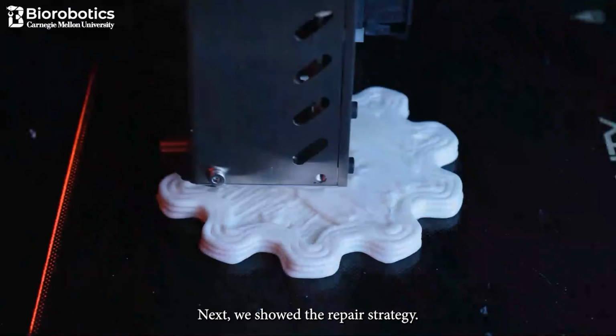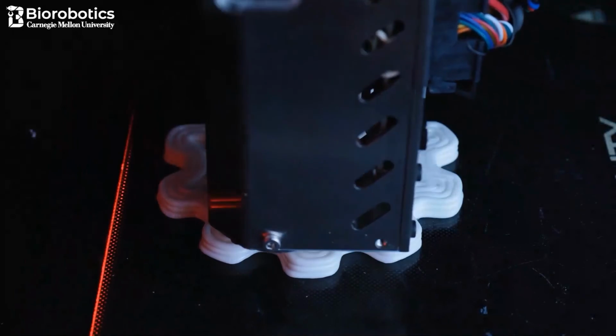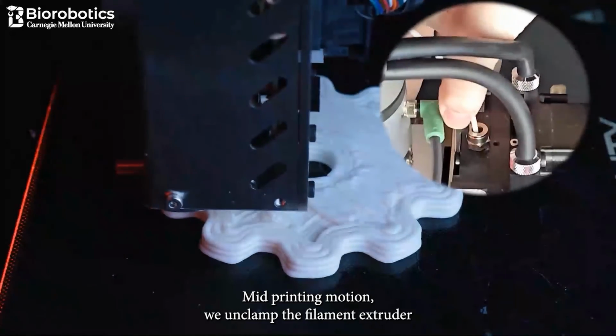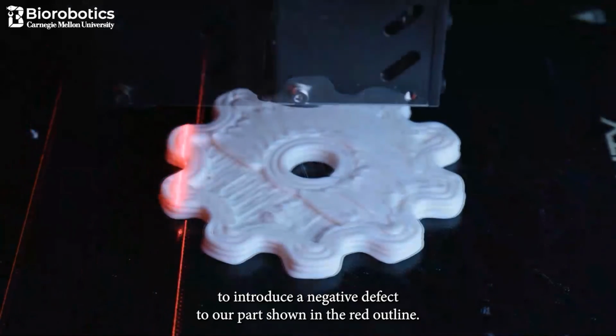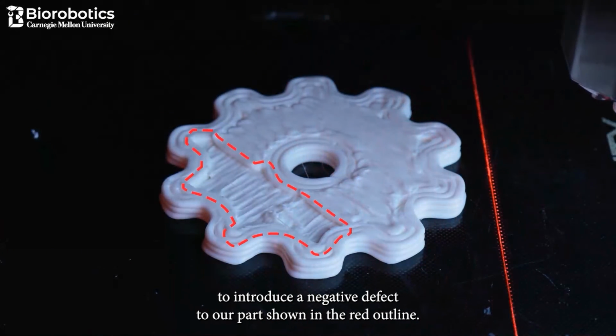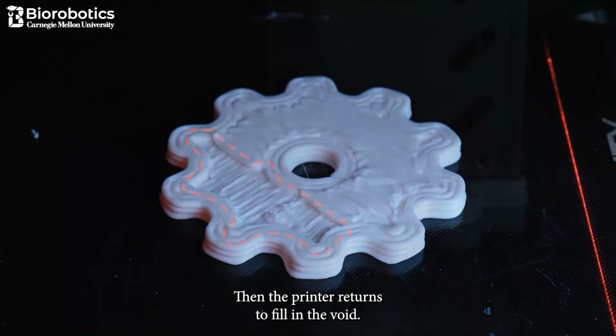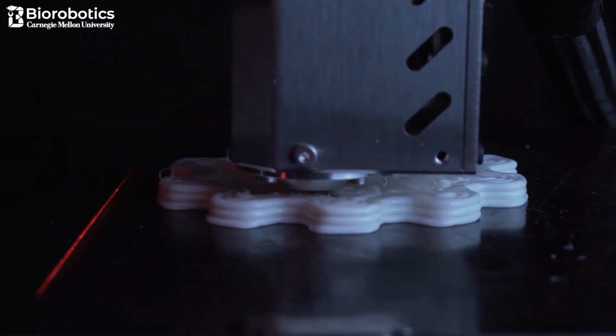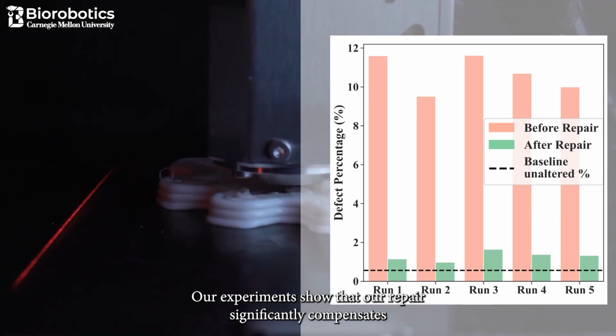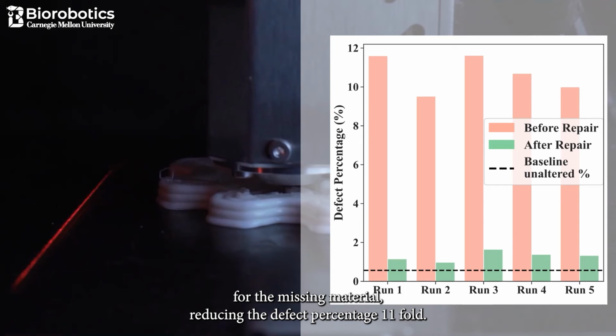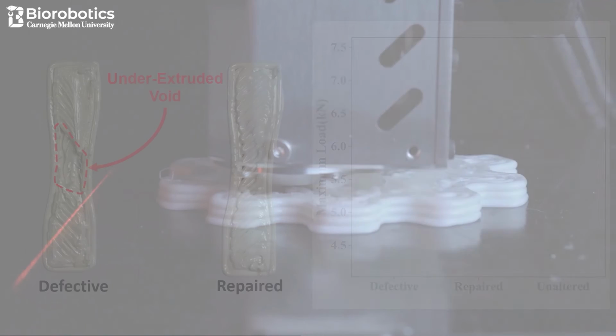Next, we show the repair strategy. Mid-printing motion, we unclamp the filament extruder to introduce a negative defect to our part shown in the red outline. Then the printer returns to fill in the void. Our experiments show that our repair significantly compensates for the missing material, reducing the defect percentage 11-fold.